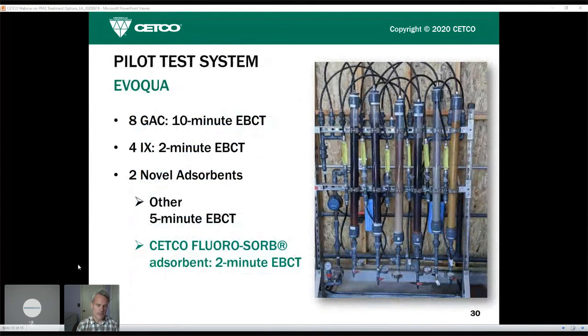So at Orange County Water District, they're performing a pilot scale experiment comparing different adsorbents to one another. These are 6-inch column tests. They're running about 8 GAC products at a 10-minute empty bed contact time, comparing it to 4 IX products at 2 minutes of empty bed contact time. And then looking at some other novel adsorbents, including the FLUORO-SORB material. One thing to note is that for this study, it's been decided to run the FLUORO-SORB very similar to ion exchange in terms of empty bed contact time. So a 2-minute empty bed contact time to evaluate the performance relative to ion exchange. And that's important in terms of the volume of media that's required to treat a given amount of water. For GAC, if you're at a 10-minute empty bed contact time, you would require 5 times more media compared to an adsorbent that was running at an empty bed contact time of 2 minutes. Go to the next slide.